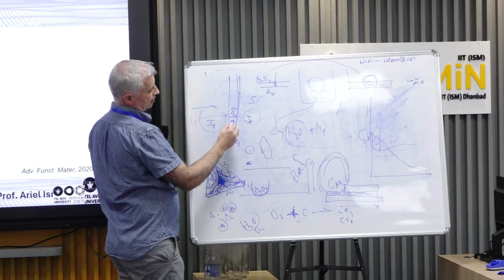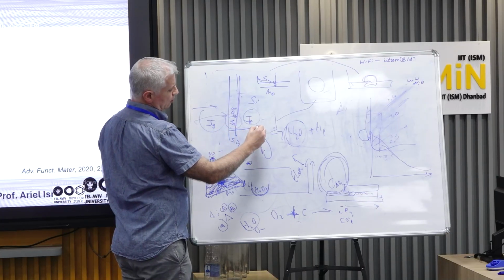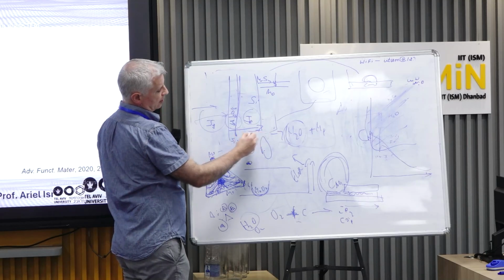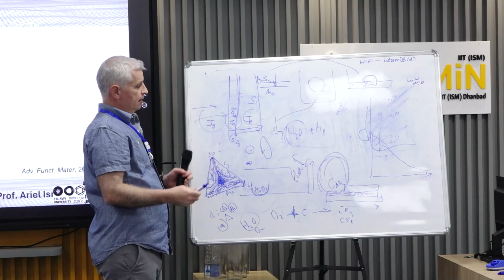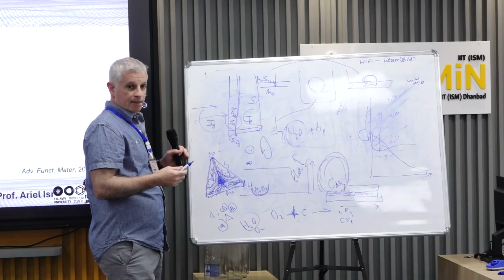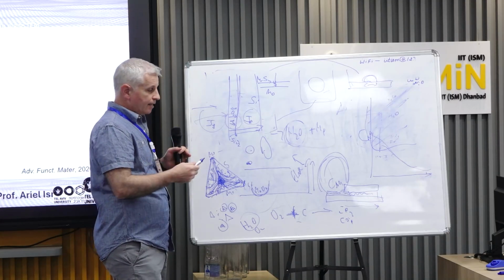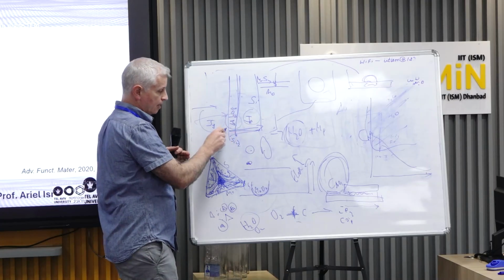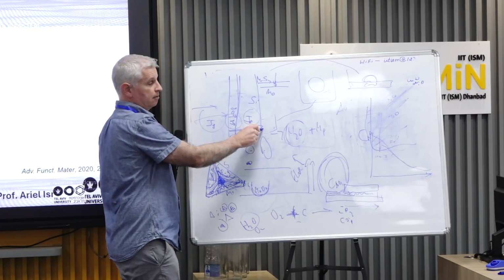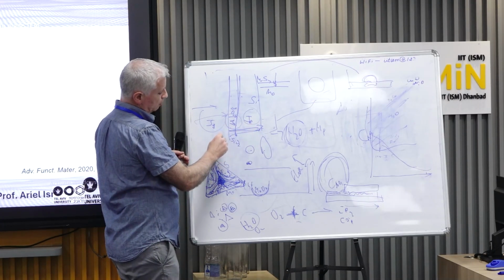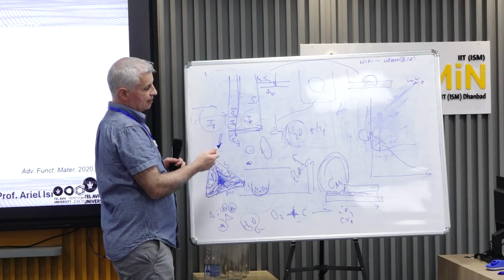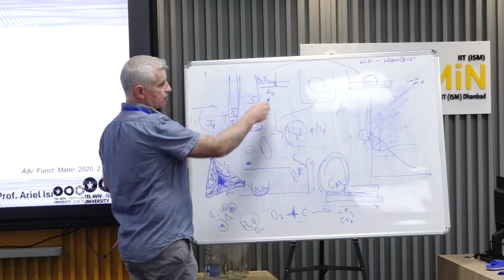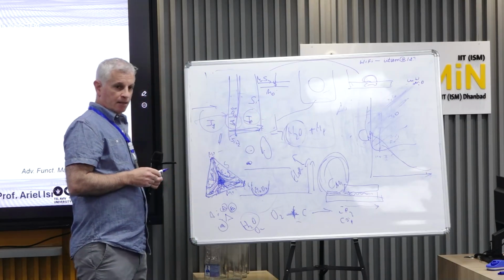So that means that, as in the silicon, when the silicon oxide layer is thick, the limiting rate is the diffusion rate, right? Because it's too thick. The oxygen needs to diffuse a lot. But when you are talking about very thin layers, the limiting step is the reaction, because the diffusion is very fast.